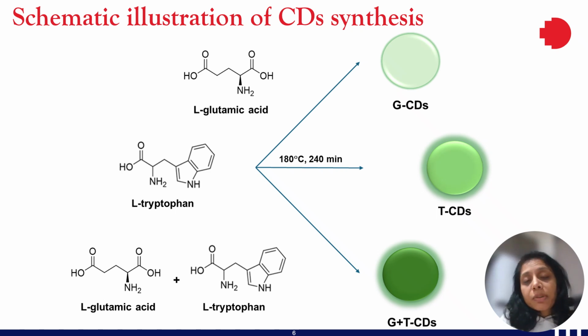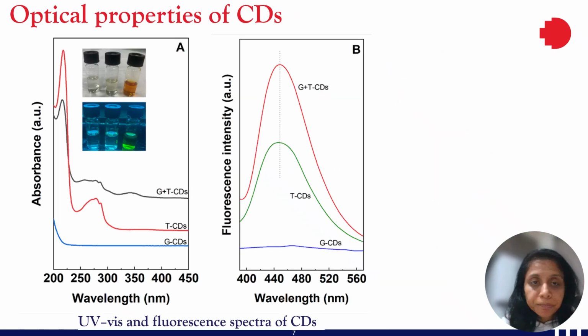Here in our study, we are typically using amino acids like glutamic acid and tryptophan and their combination. Glutamic acid contributes abundant polar surface functional groups while tryptophan introduces nitrogen doping, enhancing the optical and electronic properties of these carbon dots. So when used together, the mixture of glutamic acid and tryptophan offers a synergistic effect, combining surface functionality with enhanced optical properties. So herein we have synthesized three different types of carbon dots with individual amino acids as well as their combination via a microwave assisted approach.